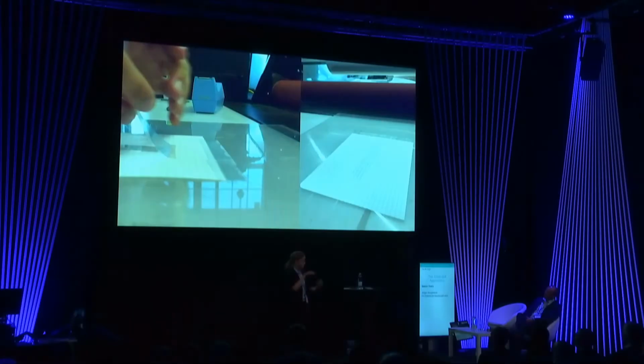And so what you do is you put your glass onto a substrate, which can be or shouldn't be paper in our case. This is how we did it the first time. So you put your glass substrate, and then you got this PET film that's coated on both sides with an adhesive. You peel a protective layer, and just as it approaches your press, you just peel off the protective coating, and then through the press, the interlayer is going to be bound into the first sheet of glass, and you do the same for the second. This is how we got a room temperature laminate.